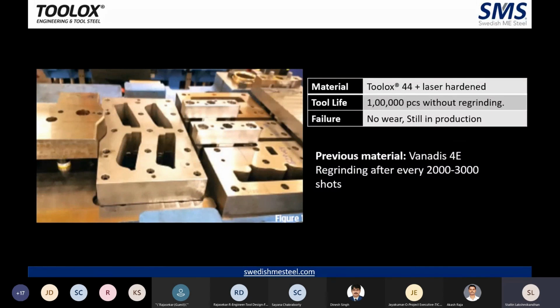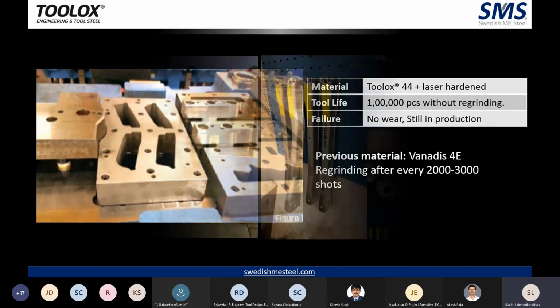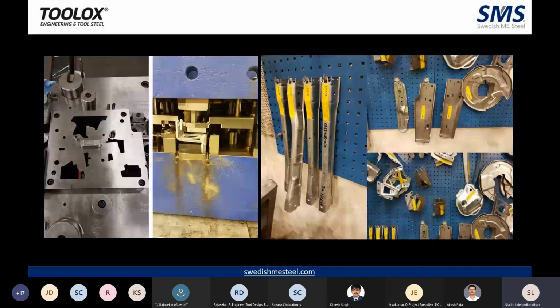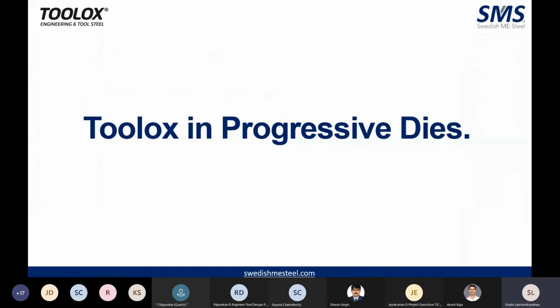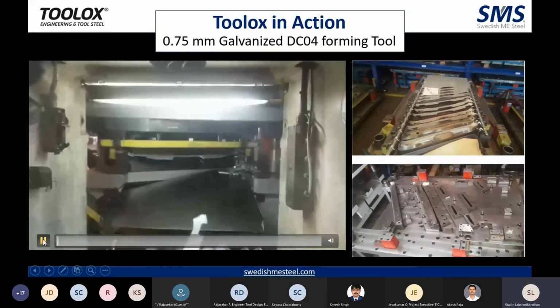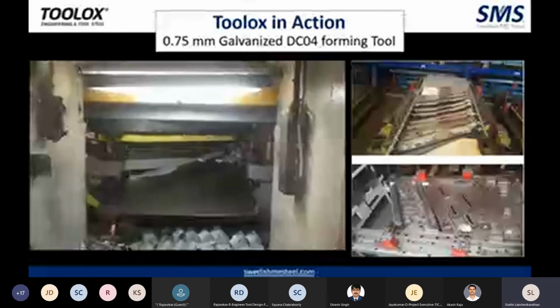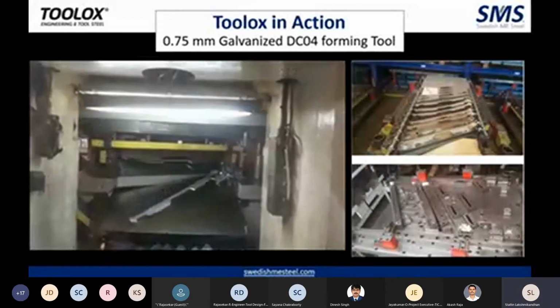As you can see, Toolox 44 plus laser hardened can also achieve very excellent results. Here it has given a tool life of 1 lakh shots without any regrinding. Previously it had to be reground every 2000 to 3000 shots, which was very cumbersome. And even though it was an expensive material, which had to be done with the same process, this was taken care of with Toolox 44. And these are some of the pieces which have been done with Toolox. Now let's see some of the Toolox used in progressive dies. This is Toolox in action in a 0.75 mm galvanized forming tool.